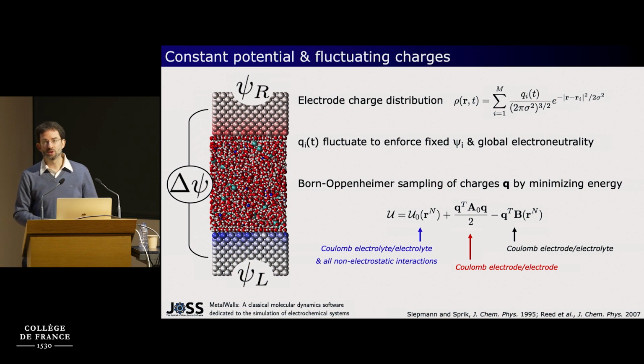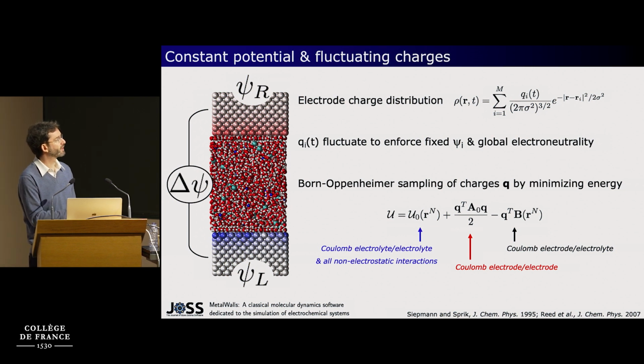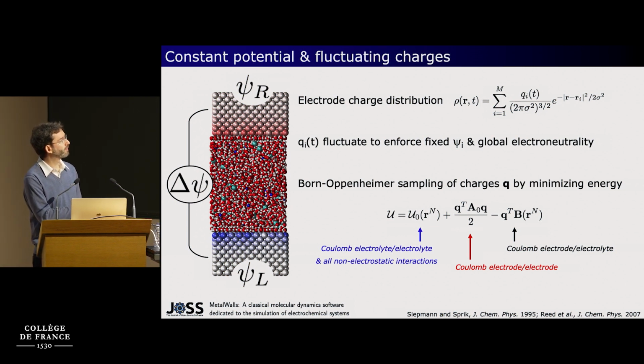And the way the charge fluctuates is that at each time step of the molecular simulation, you recompute the partial charges, so the magnitude of each electrode atom charge. You recompute it in order to enforce the constant potential and global electron neutrality constraints. And this involves minimizing the energy under that constraint with respect to the set Q of all the partial charges of the electrode atoms. And this energy here contains both non-electrostatic interactions, which do not depend on the partial charges, and also electrostatic interactions, which contain electrolyte-electrolyte interactions.